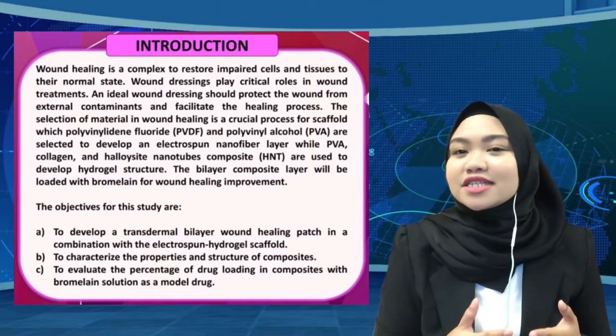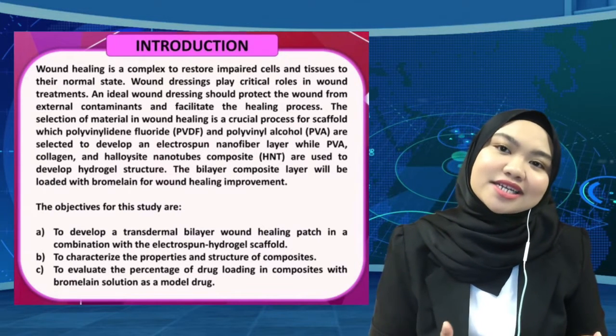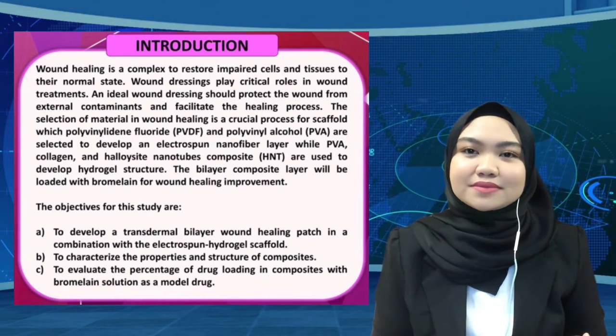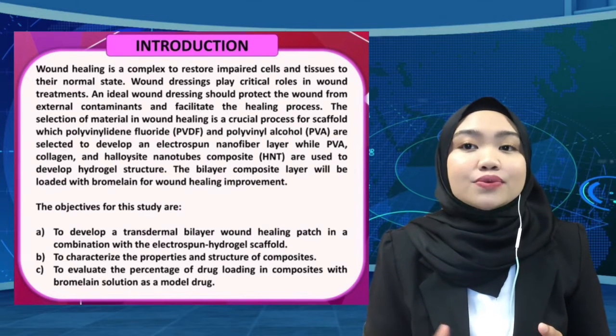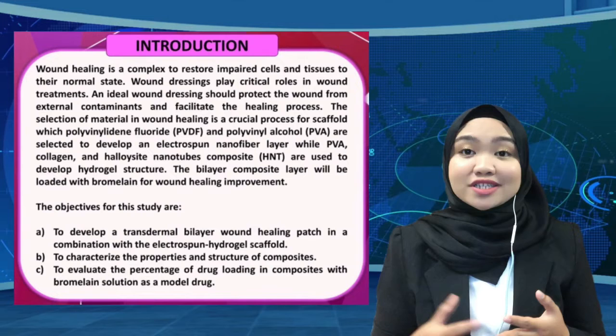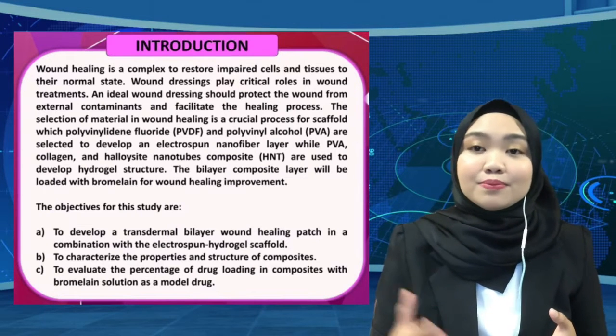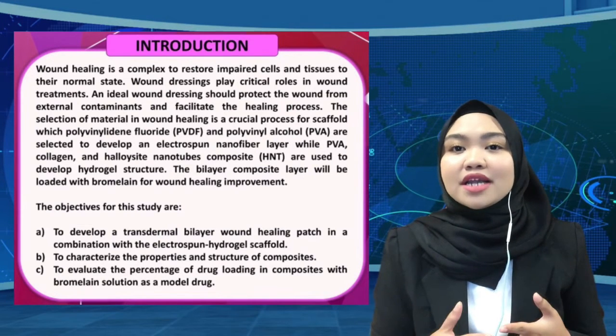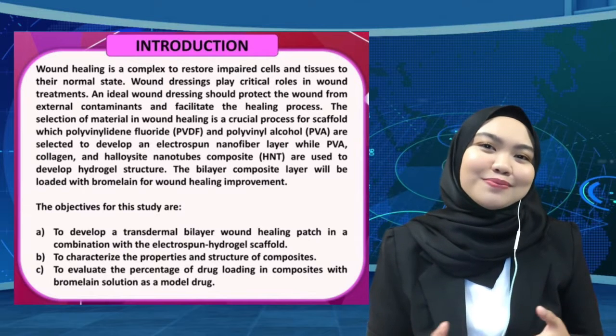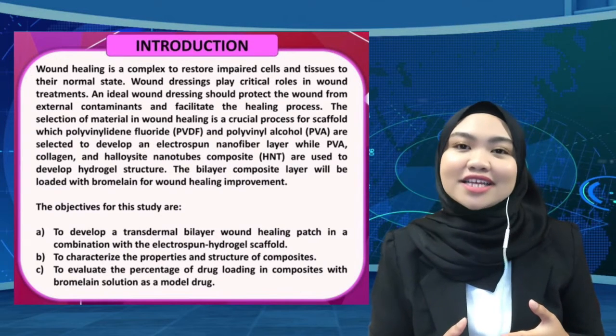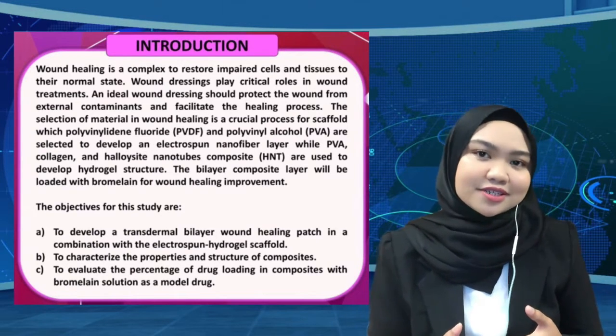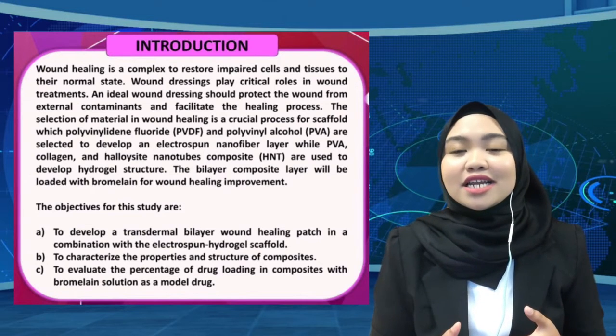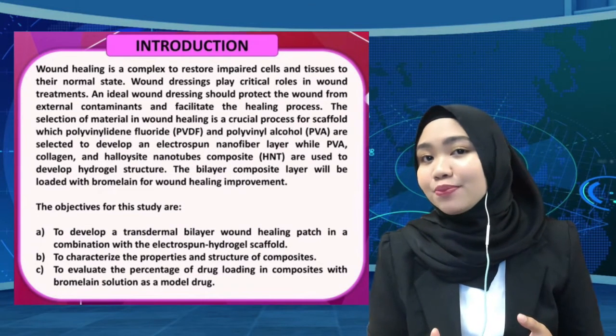The composite dressing is made up of multiple layers, and each layer is biologically distinct. The selection of material in wound healing is a crucial process for the scaffold, in which PVDF and PVA are selected to develop an electrospun nanofiber layer, while PVA, collagen, and HNT are used to develop the hydrogel structure. The bilayer composite layer will be loaded with Bromelain for wound healing improvement.